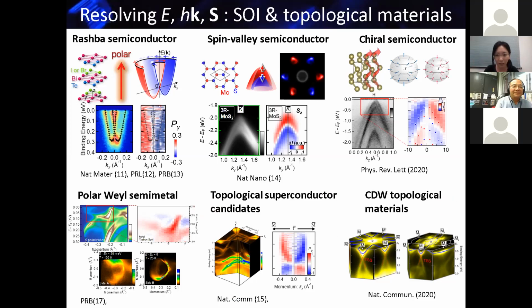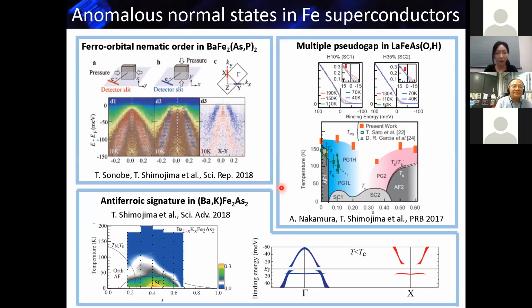And recently, we also worked on some CDW, charge density wave materials. Once we switched on the charge density wave, the topological surface state disappears. And this CDW transition induces a topological transition. So by utilizing this ARPES, we can find many interesting materials like this. Okay. Oh, sorry. And also, this is also some summary.